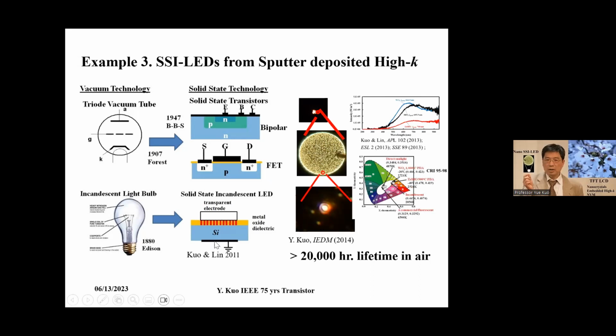And this kind of device has a long lifetime of 20,000 hours, under operation in air without any passivation. It's more than 20,000 hours. And after several PhD students graduated, we stopped the testing because it's still running.